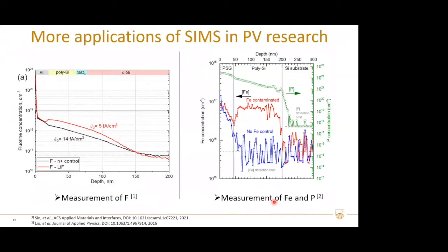In addition to hydrogen and deuterium, researchers in our group have also applied SIMS to measure fluorine, phosphorus, and iron. Our recent study has indicated that fluorine could potentially replace hydrogen to passivate dangling bonds and improve surface passivation. Previous results have shown that surface passivation can change with diffusion of hydrogen, leading to unstable performance during thermal treatment. The use of fluorine might help enhance the stability of silicon solar cells, and we are performing more experimental work for further study.